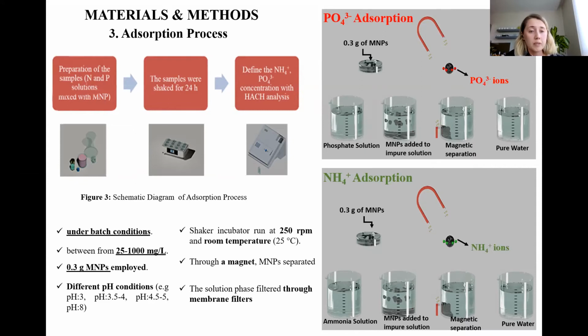And after the adsorption was carried out, we defined the ammonium and phosphate concentration in the solution. We employed a magnet to separate the magnetic nanoparticles. At the end, the spectrophotometric measurements were carried out.